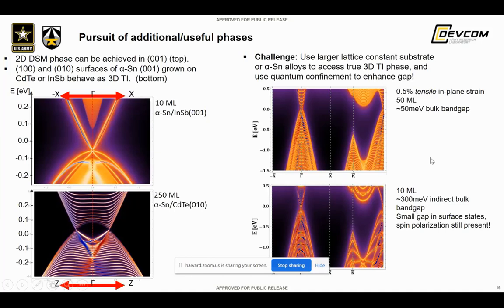So you can go from seeing a Dirac semi-metal to large band gap 3D topological insulators just by using quantum confinement, if you can grow tensile strained, in-plane strained alpha-tin. So this can be done. There are some techniques that can be used to address this, but we'll talk about that in the next couple of slides.